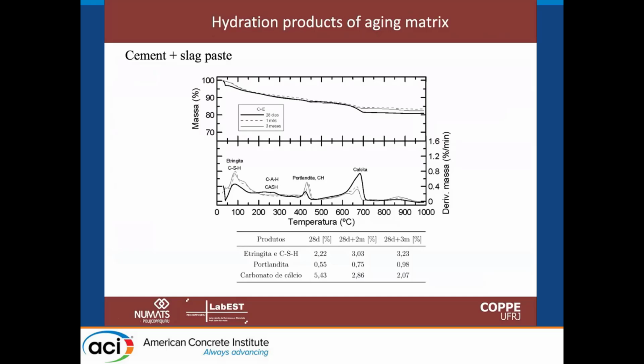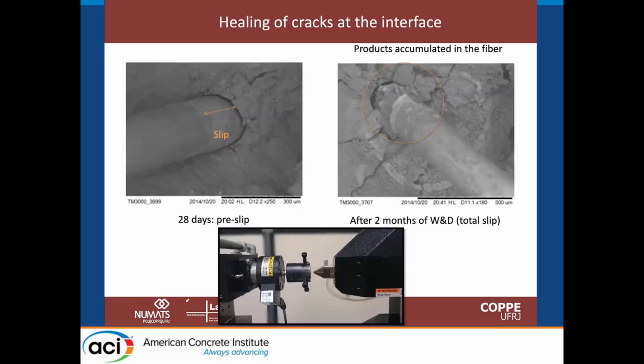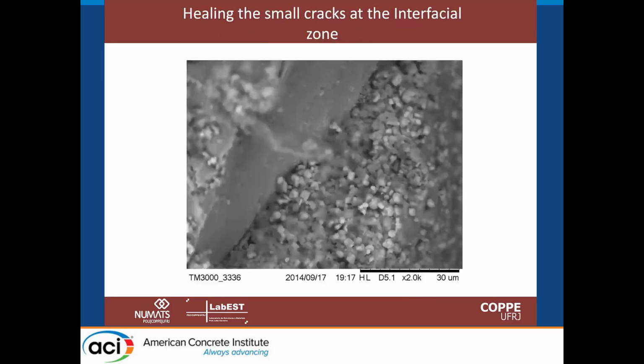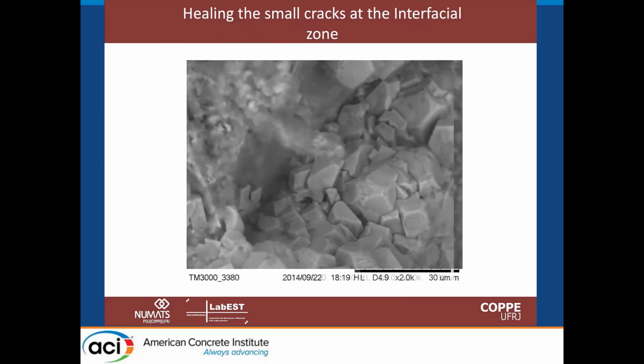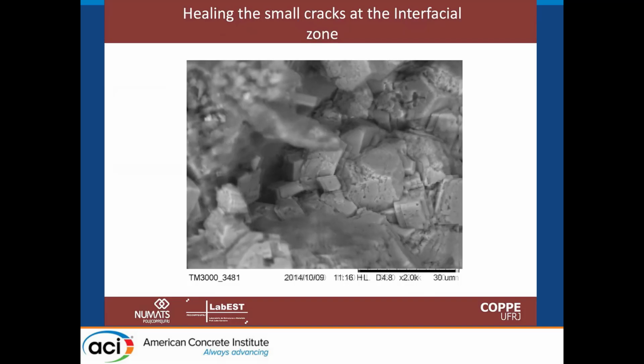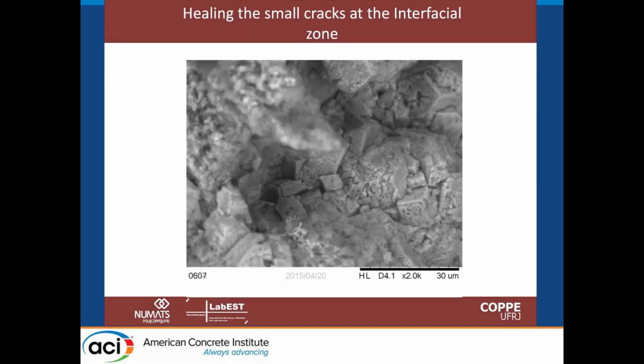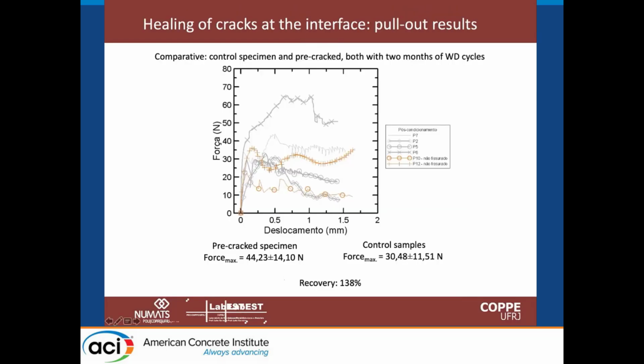transporting water from one side to the other of the crack, and then deposition of unreacted materials can happen. This is quite the case of ultra high performance materials, where we have a large amount of unhydrated cement, so we can close cracks. And we did some tests here just to see the interface of these steel fibers. Where we have thin micro cracks, you see here that the densification of the interfacial zone by these products completely healed the interface. We did a pull-out test after healing, and we see here this response. This is the non-cracked, the reference one. In some cases we can have a response that goes above this behavior, or very much keeps the same force for pull-out.